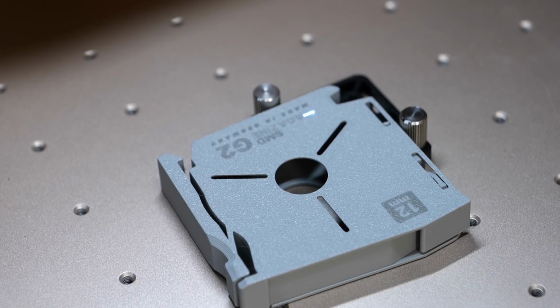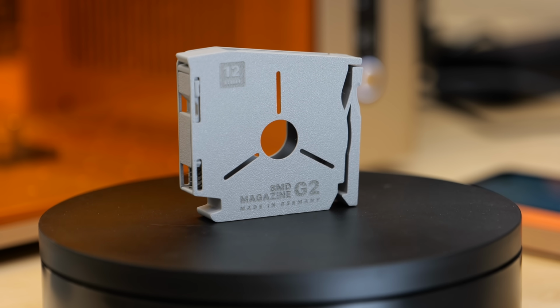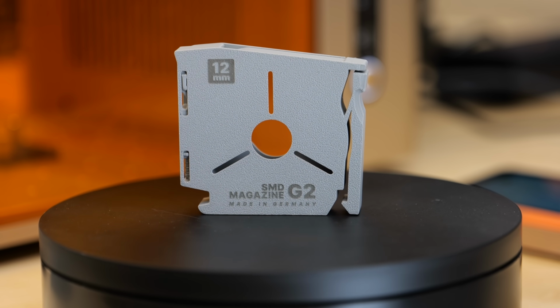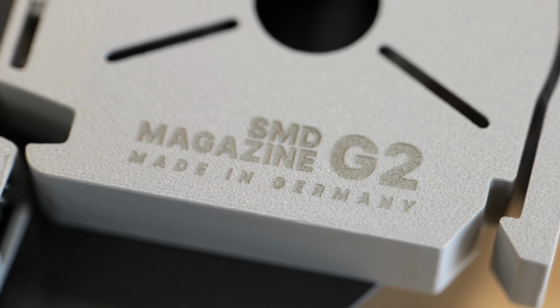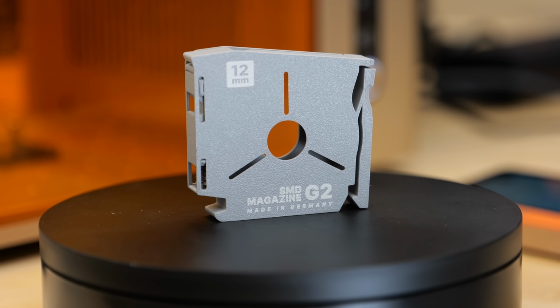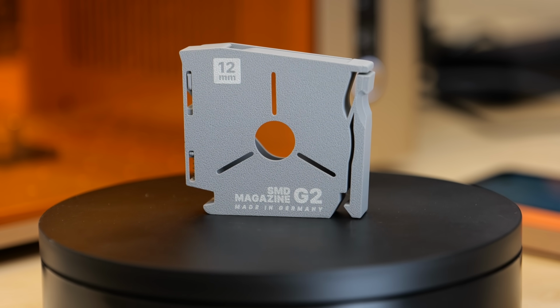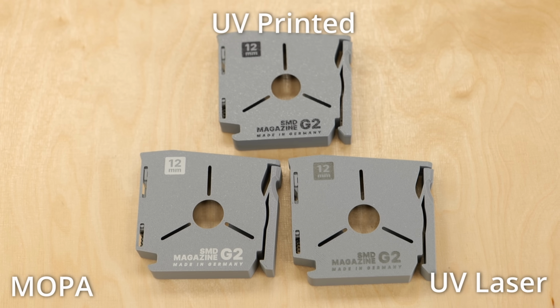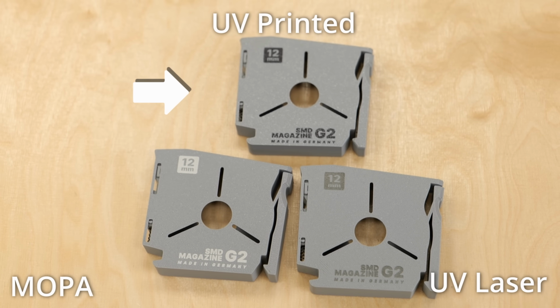With the chosen settings, I engraved 2 actual SMD magazines. The UV marked one had a darker engraving. It actually didn't look too bad because the shiny molten surface added some additional contrast. The MOPA marked one was lighter and looked a bit more defined. Both were acceptable, but neither looked as good as the UV printed reference.